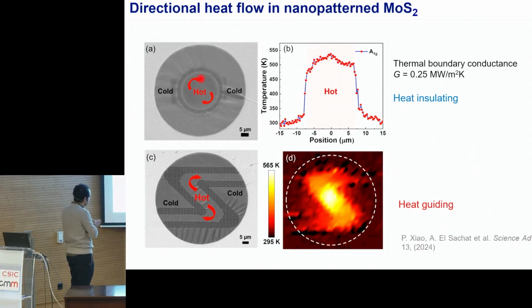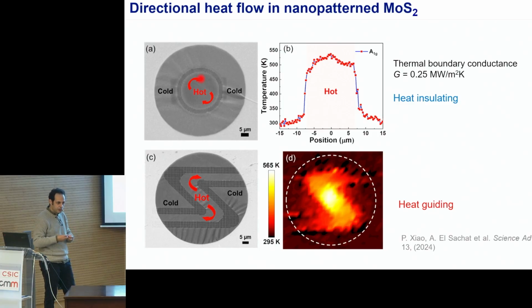Then you see in the bottom that we can create some specific patterns again in our membrane, and the heat flux and the heat flow that we created here in the hotspot actually follows the patterns of the FIB patterns that we created. So this is a nice demonstration to show that nanopatterning can actually guide the heat flow in pre-specified directions, and this is something interesting if this result is working also in devices where we have hotspots. So the idea is that if we can integrate these molybdenum disulfide flakes on devices and see a similar trend. Of course, it will be more difficult because we have the effect of the substrate, but this is the first demonstration that nanopatterning can be used for this purpose.